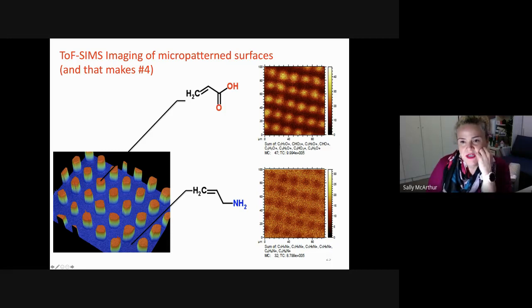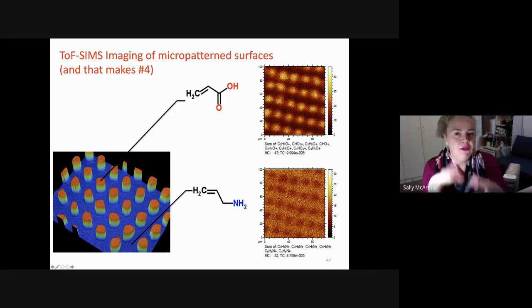elemental nature of the surface, but we can see that we've got patterns where we've got the acid on the surface and the background is the amine. Now, if you remember, the acid surface should enable us to induce a collapse of a lipid vesicle, while the amine surface should enable us just to have vesicles intact on the surface.